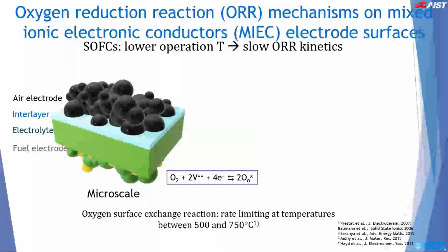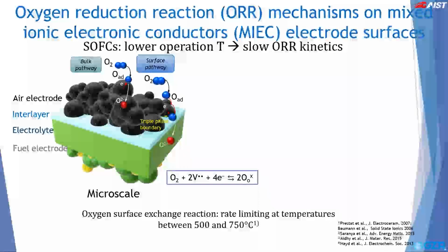Typical cathode materials are mixed ionic electronic conductors. This means that the oxygen reduction reaction that occurs on cathodes proceeds via a bulk pathway, wherein the oxygen atom receives an electron from the cathode and is then converted into an oxide ion and incorporated through the cathode bulk, or via the surface pathway, wherein the oxygen atom diffuses across cathode surfaces, reaching the triple phase boundary, where it is then converted into an oxide ion. Here, the triple phase boundary is the region where the cathode, electrolyte, and gas phase converge.